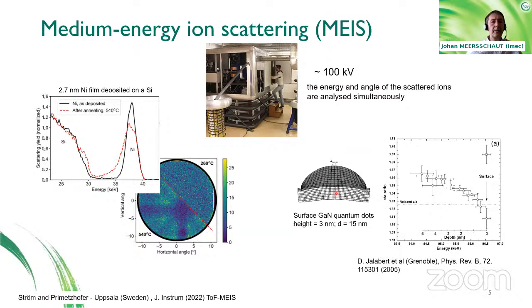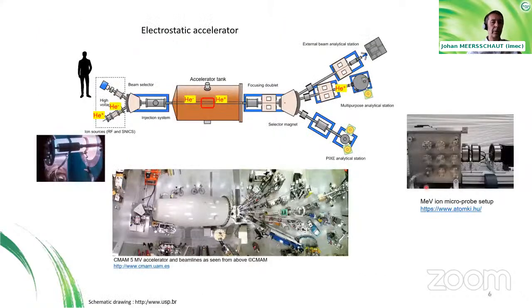So you see that for these MEIS spectra, you are quite limited to a depth of about 5 nanometer, but in practice, we experience samples that are much thicker than that. And to probe these larger depths, we need higher energies. And then we end up with the large infrastructures, as we talk about tandem accelerators that you will find at several locations within Europe. You see here the size related to the size of a human. So we are talking about a hall, the size of an experimental hall, to host such an experimental setup. And the typical setup is composed of a helium ion source or another ion source for heavy ions.